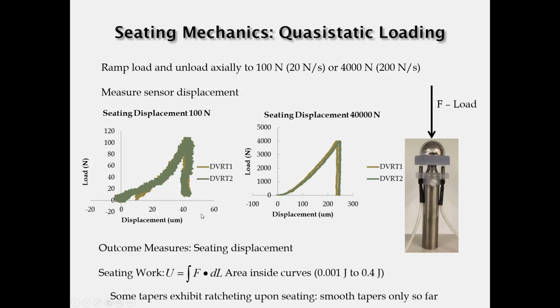And what you can see in these plots is that the head sits down onto the taper. In the case of 4,000 newtons, that's roughly a 250 micron seating displacement. And with 100 newtons, you only get maybe 40 microns of seating displacement. So these curves represent the nature of the engagement mechanism between the tapers. And there are elements of it that are important, including the area inside the curve, which is essentially the work done to seat that head.